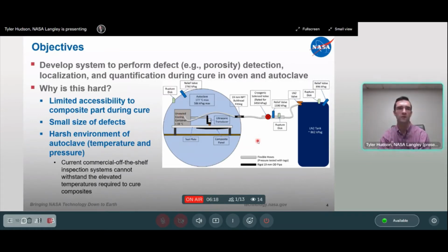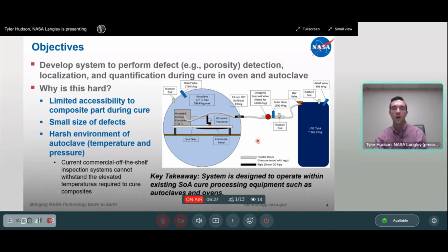And it's a really elegant cooling design in that most autoclaves are a nitrogen environment, but this could work in autoclave or oven. And really the takeaway is the system is designed to operate within existing state-of-the-art cure processing equipment, such as autoclaves or ovens. It's designed to be bolted onto your existing production technique. You're not going to have to completely change the way that you're making your composites. This is just adding data to your production system.